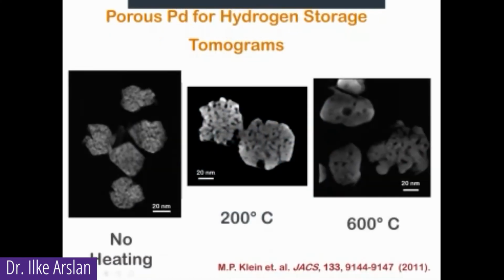So what we figured out was that as you start heating them, the pores do collapse and they become bubbles, like you just saw in the tomogram. So these are slices through the reconstruction. And this is a very good indication of what's happening.